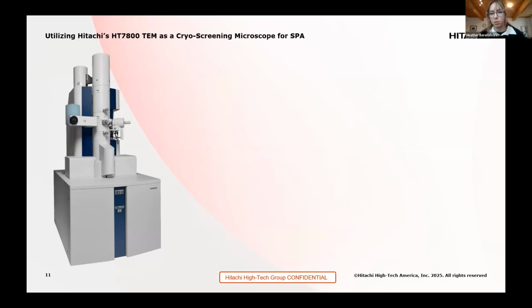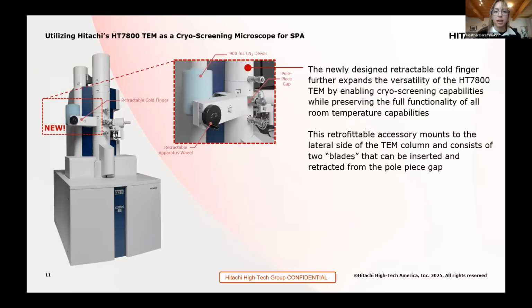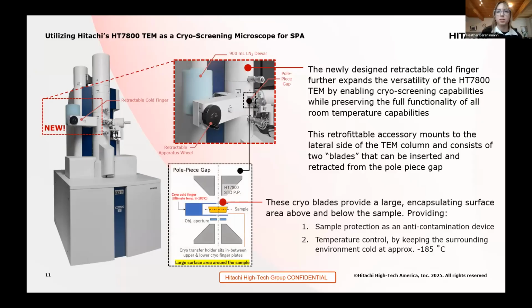So now that we determined the microscope, we also included a new retractable cold finger design that expands the versatility of the TEM. With this retractable system, we're able to preserve the full functionality of all room temperature capabilities, but now when we want to do cryo screening, we can insert what we call blades. These blades are inserted into the pole piece gap of the microscope and are located above and below the sample. This style of blade helps the sample by acting as an anti-contamination device and also as temperature control, keeping that surrounding area cold. And so when we're ready, we can go from room temperature applications to cryo screening capabilities.